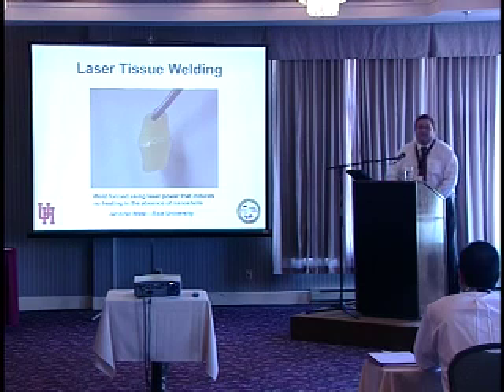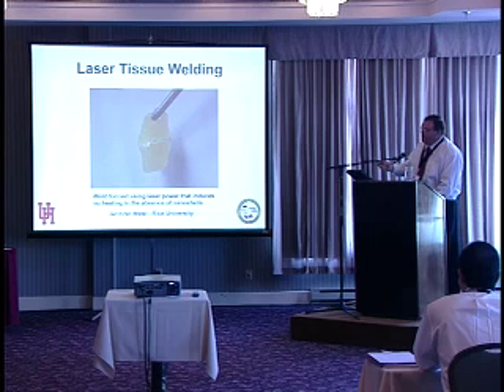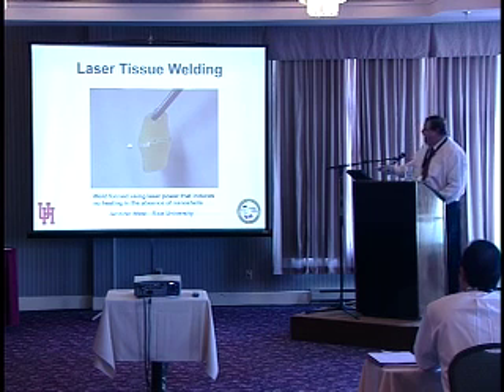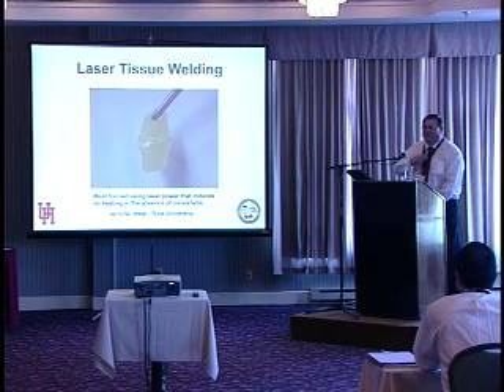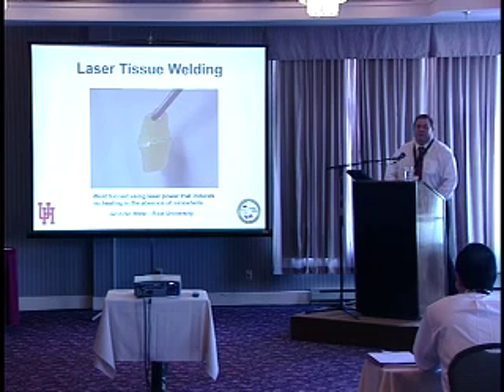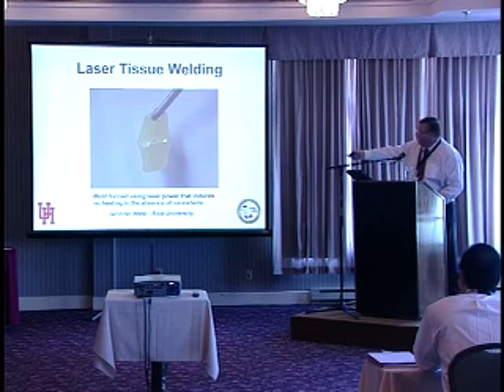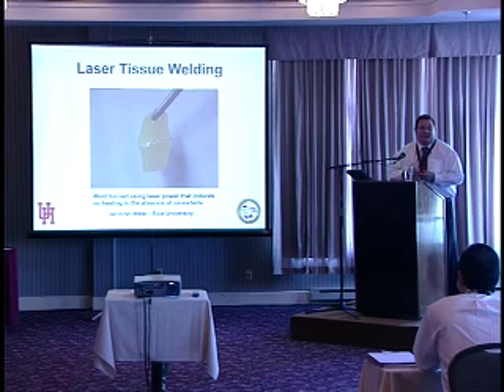So some work that's already been done, my colleague Jennifer West at Rice University has demonstrated the technique of laser tissue welding. And so what you do here is just take a piece of tissue and slap on the surface of it some nanoparticles, and then you shine an infrared light, and the nanoparticles get hot and fuse the tissue together right at the point where you put your nanoshells. Okay, and so the only part that gets hot are the nanoshells themselves, so you can really localize the